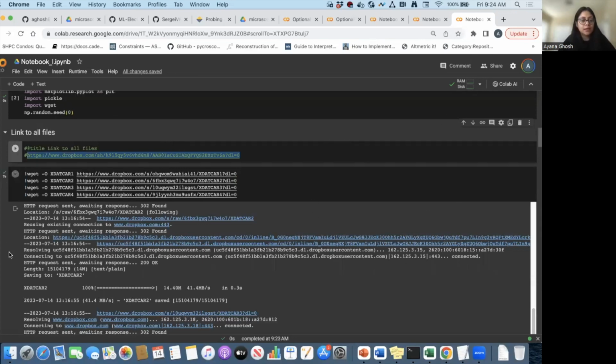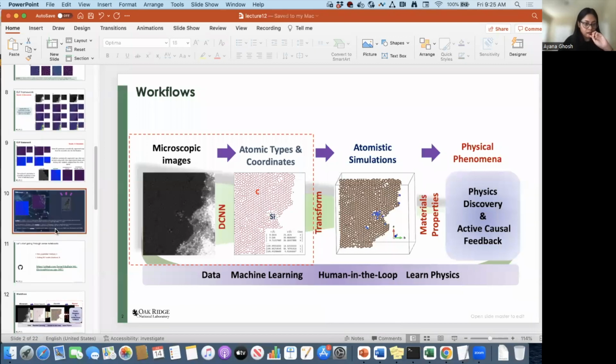So the simulation part, as I mentioned before, was performed with VASP, with ab initio molecular dynamics. So we have run AIMD with a 200 atom graphene supercell at 300 Kelvin with the temperature constant. And then for every simulation, we also take out one atom each, up until there are like 10 or 20 atoms left in the cell. And then we gather that data, all of the XDATCAR files, so all the trajectory information, and then read that to generate our full training data set.